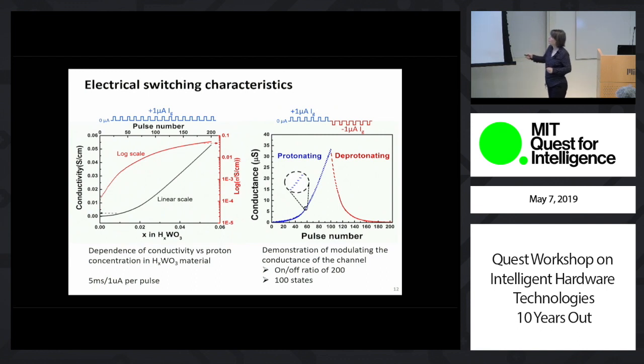Okay? So, again, summarizing some of the electrical characteristics of this device, conductivity as a function of pulse, or translating pulse to hydrogen content. By using these 1 microamp, 5 millisecond pulses, we could protonate tungsten oxide from nominally 0 to about 0.06 per formula unit, and that gives rise to more than 2 orders of magnitude change in conductivity.